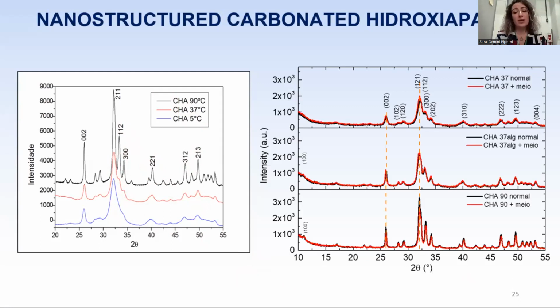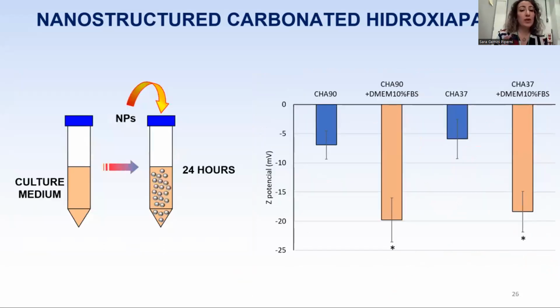It is also important to do the physical-chemical characterization before and after culture medium contact. So these diffractograms show the pure materials in the black line and the materials after culture medium in the red line. And as you can see in the images, no difference in crystallinity after culture medium exposition was observed. However, we know from the titanium experience that it is possible to have protein adsorption on the material surface. So to check this, we tested the Z potential, a technique based on the ionic concentration on the surface of the particle. And we see the protein adsorption on the material surface.